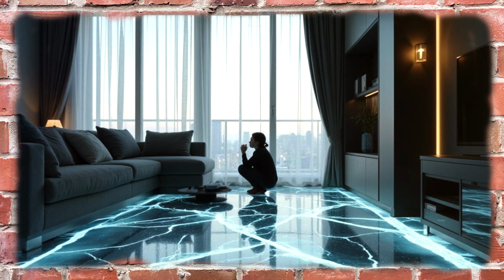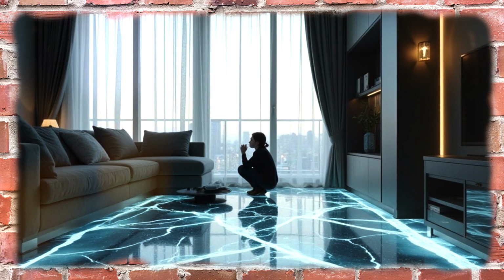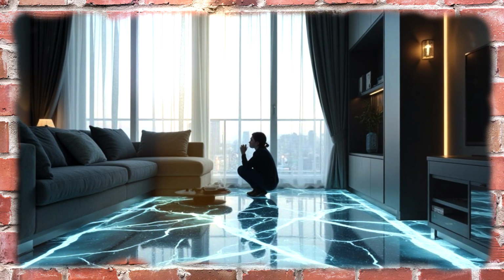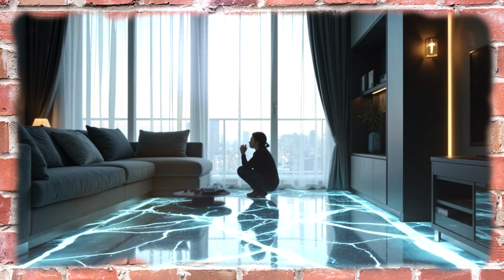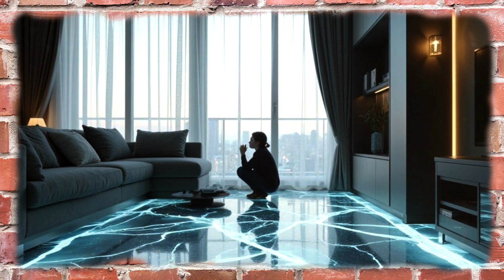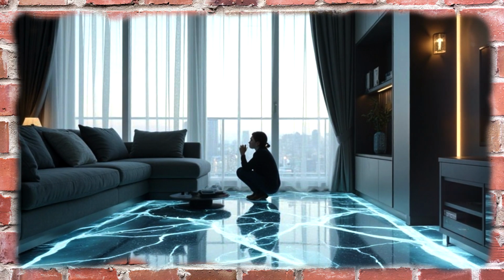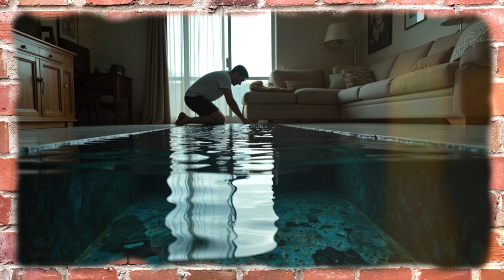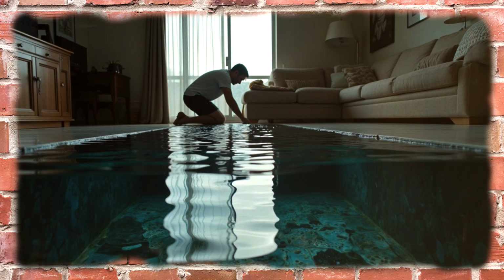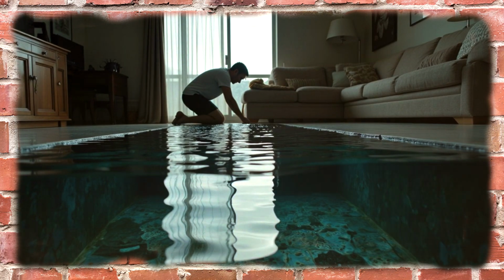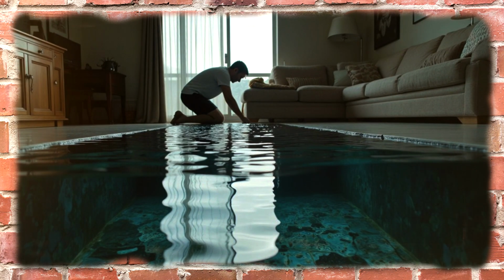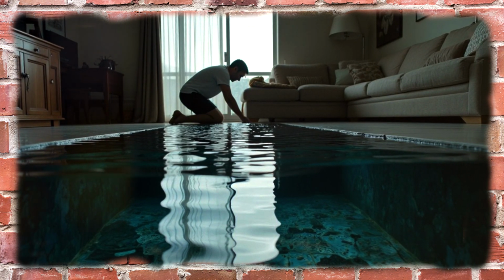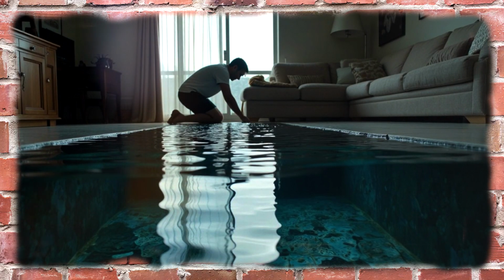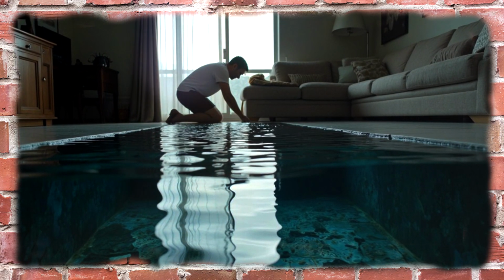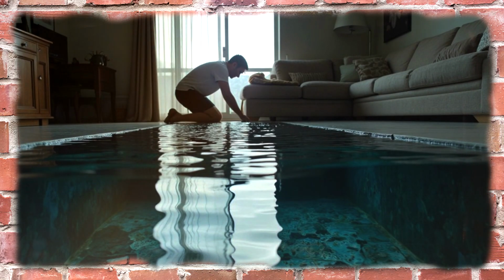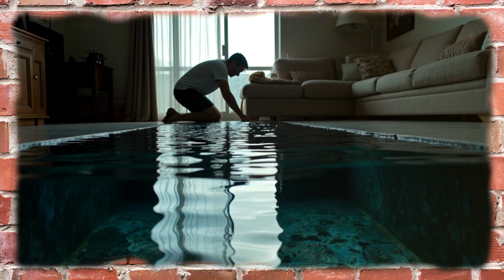And of course, there is leveling. This is where the needle comes into play. Not a medical one, but a special roller with long stainless steel needles that is rolled over the fresh resin to burst the bubbles and create a self-leveling effect. But even here there is a secret, because you need to roll it not immediately, but 5 to 7 minutes after pouring, when the resin has already started to thicken but has not yet lost its fluidity. If you do it too early, the needles will leave marks, and if you do it too late, the bubbles will already be frozen inside.